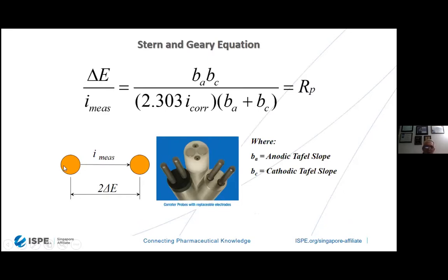And what we're doing is this eye measurement across these two cathode poles using what's called the Stern-Geary equation from 1957. This allows us to show what the corrosion rate is and how that corrosion develops over time. That's how we derive the Rp, which is the polarization resistance. We can measure this down to single nanometer levels and even less. Only the probes themselves are sitting in the water. The body of the probe remains outside of the hygienic clamp.